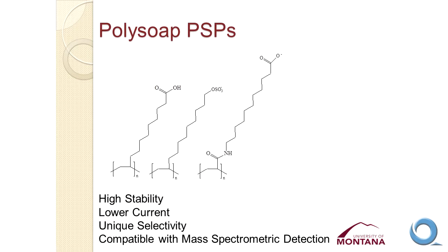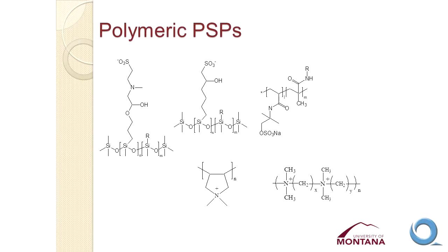The first materials we looked at were these so-called polysoaps, and really all they are is a surfactant that has a polymerizable group on the end of the hydrophobic tail. So once they form micelles, you can polymerize them in the structure of micelles, and then isolate them as these polymeric micelle structures. They have, of course, very high stability then. We can use very high concentrations of organic solvents and get very nice separations of hydrophobic compounds. They generate less current, so in principle, we ought to be able to do faster separations and separations with higher efficiency. We showed that they provide unique selectivity and also that they are, in fact, compatible with mass spectrometric detection.